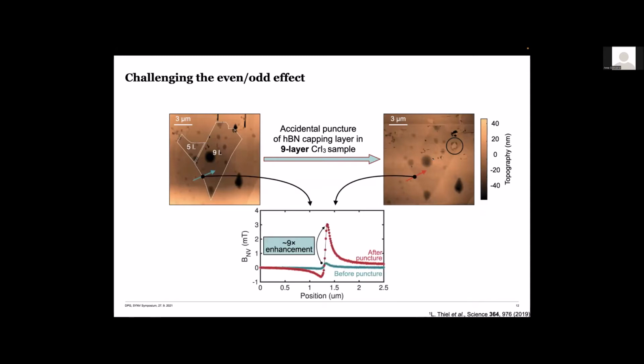Instead, what happened after this puncture was that we observed that the magnetization was increased by puncturing this flake. And you see this here just by line cuts across these edges, how the magnetization or the stray magnetic field strength here increased essentially by a factor of 9. And now, of course, this increase by a factor of 9 is indicative in the case of a 9-layer sample that we turned this antiferromagnetic interlayer coupling into a ferromagnetic interlayer coupling. So that's what the data suggests. The question is, of course, why that happened.